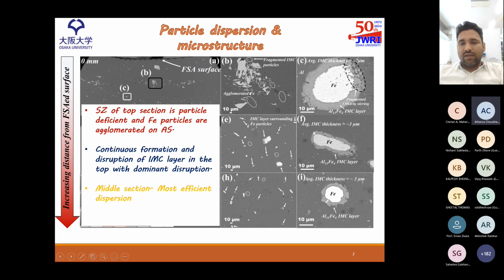And there is a continuous disruption and formation because in the top section, the temperature is also higher for the diffusion of iron atoms into aluminum. So the reaction is also higher. So the chances of formation of IMC are also more prevalent in the top section, but simultaneously the stirring action is also more dominant. So that's why the disruption of this layer also takes place simultaneously with the dominant disruption. And the middle section is the most efficient dispersion we have observed.